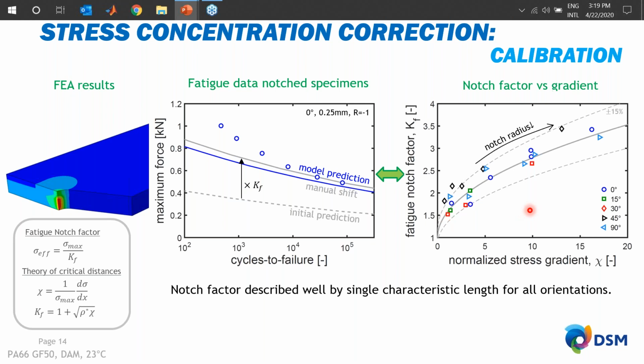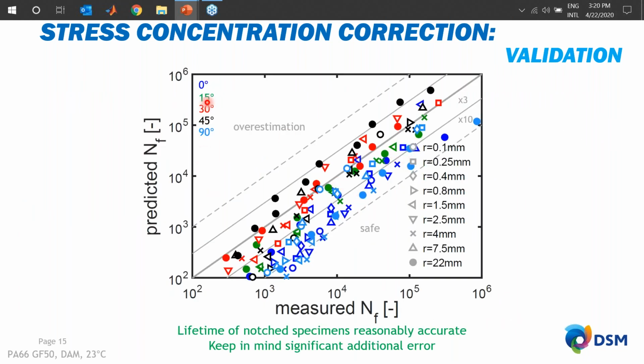But one consequence, of course, is that we are scaling our local load. You all might appreciate that the lifetime is very sensitive to stress. That means that we have to take into account that this plus minus 15% is actually also plus minus a factor 5 in life that we introduce. But nevertheless, with that framework, as you can see over here, again, the measured versus predicted lifetime describes the lifetime for a huge range of notch radii and a lot of different orientations very well. So we introduce a bit more error, but again, we can describe the lifetime of notch specimens reasonably accurately.